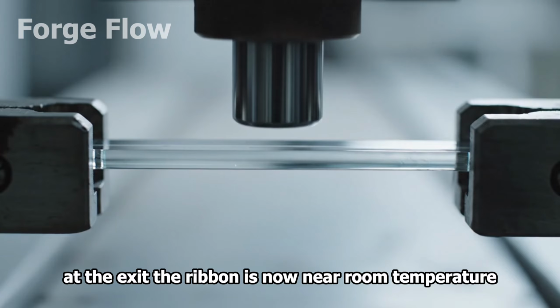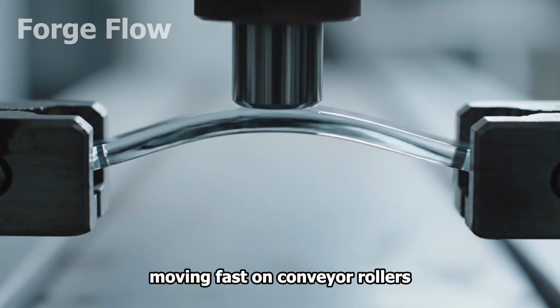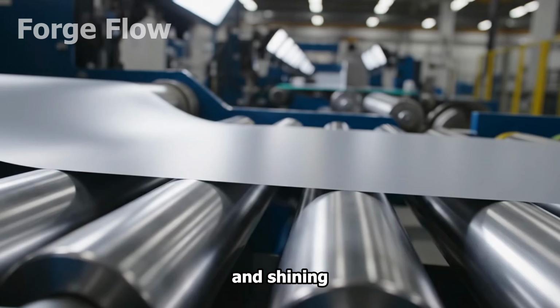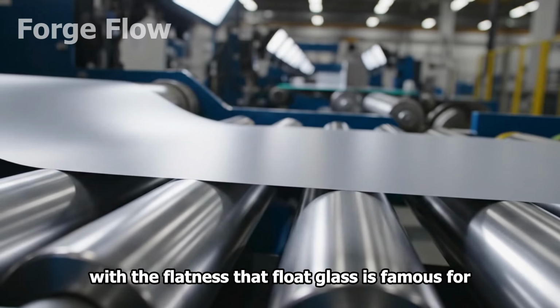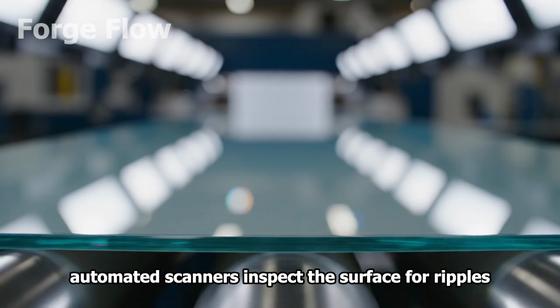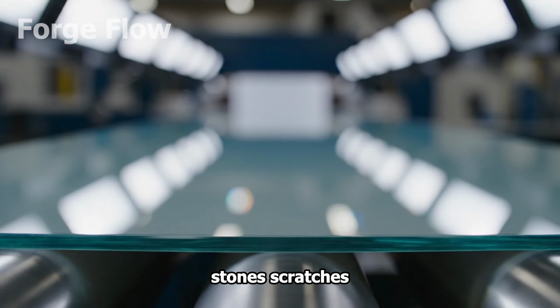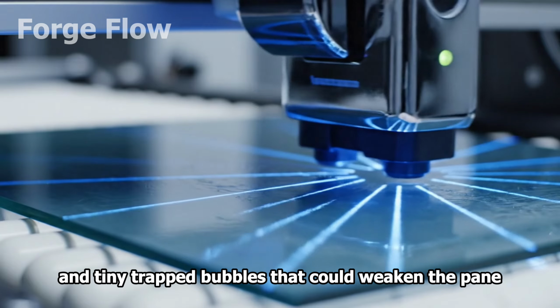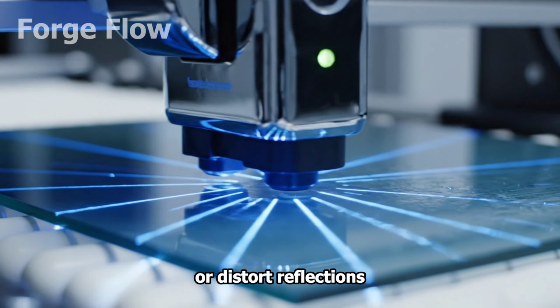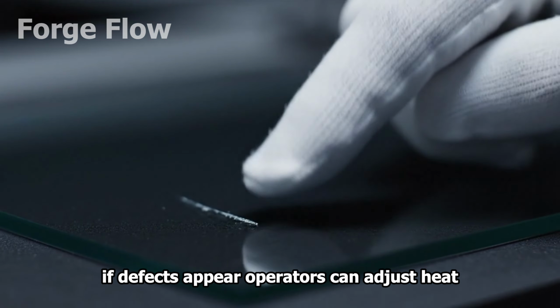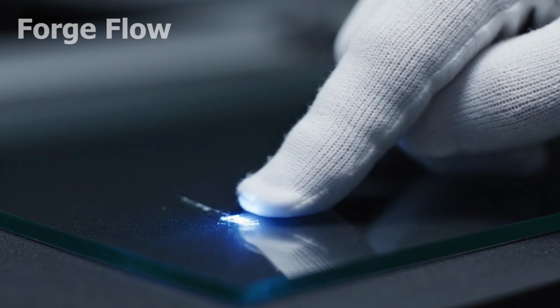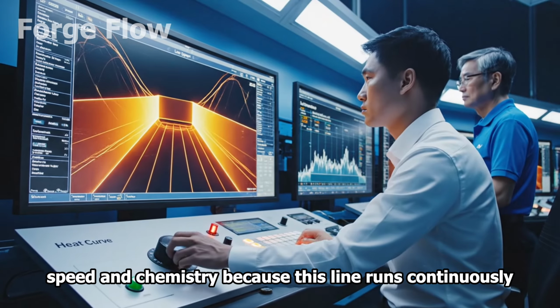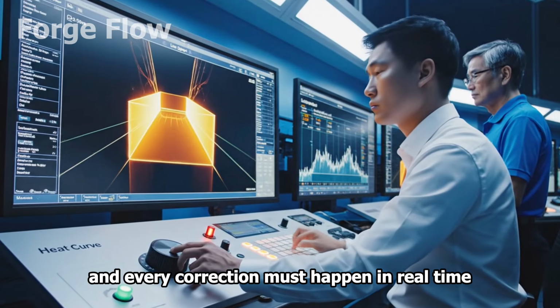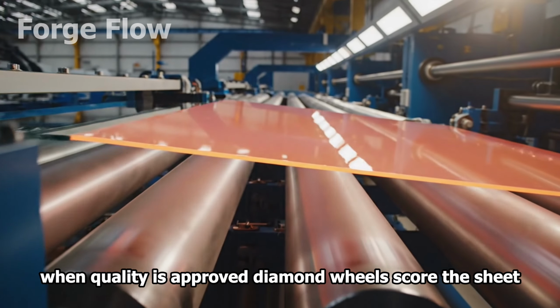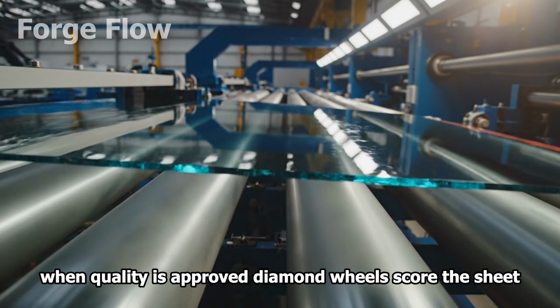At the exit, the ribbon is now near room temperature, moving fast on conveyor rollers and shining with the flatness that float glass is famous for. Automated scanners inspect the surface for ripples, stones, scratches, and tiny trapped bubbles that could weaken the pane or distort reflections. If defects appear, operators can adjust heat, speed, and chemistry, because this line runs continuously, and every correction must happen in real time. When quality is approved, diamond wheels score the sheet.